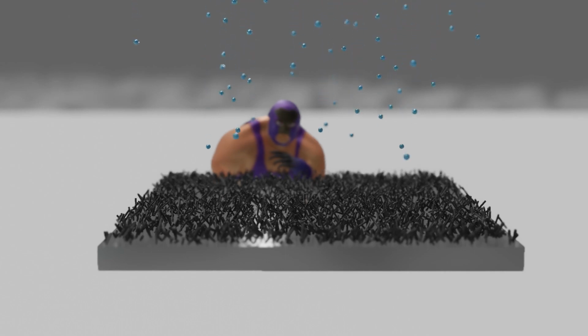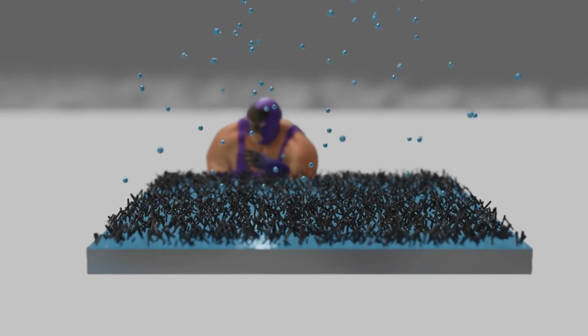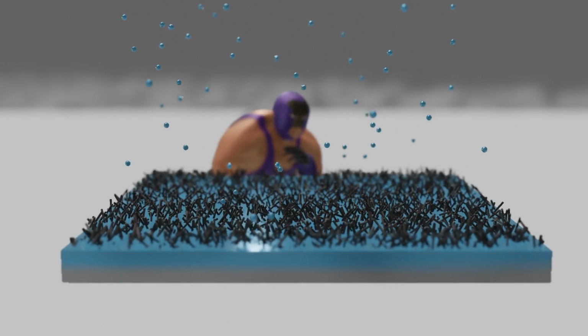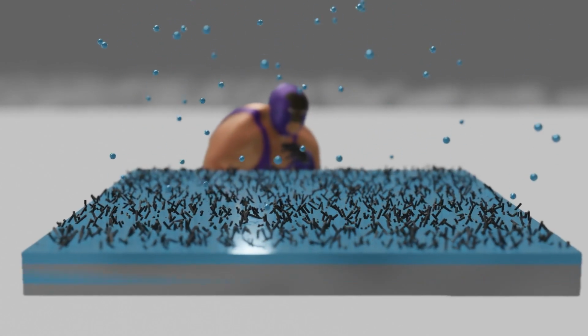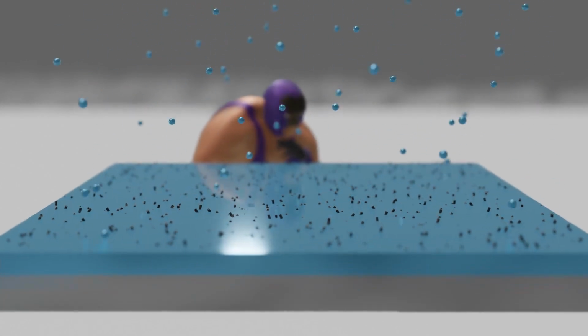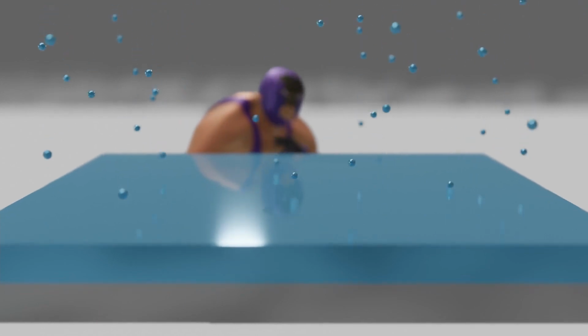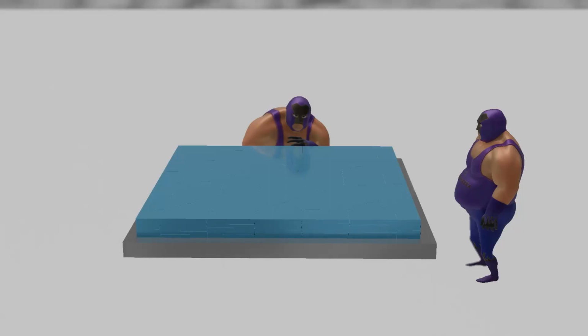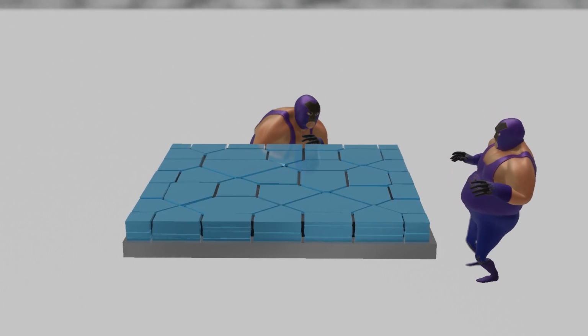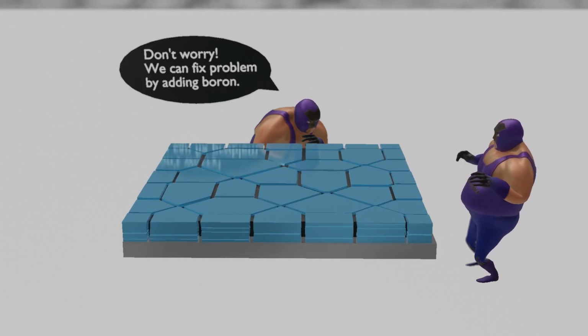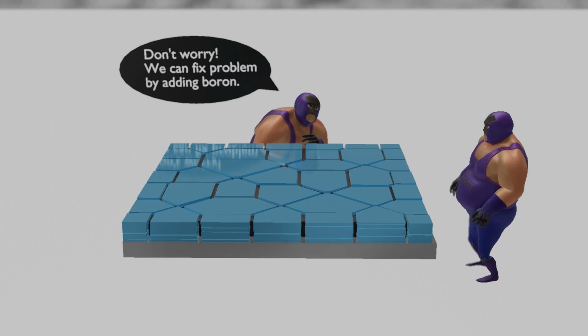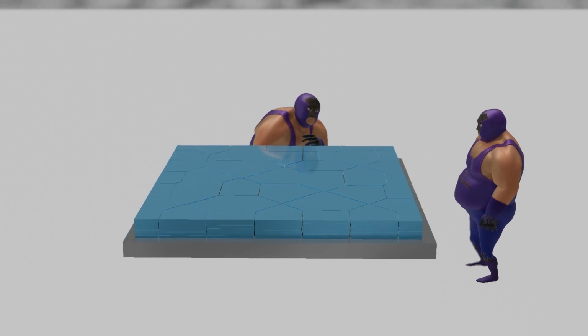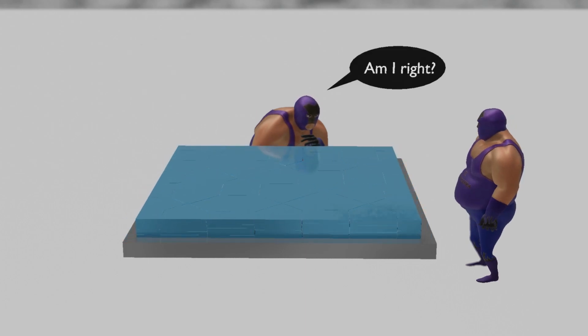Let's take another look. It has recently been shown that the carbon layer of the thin film coated on aluminum foil surprisingly helps sodium ions grow uniformly when charging the battery and inhibits the growth of pointed dendrite forms. Another important recipe is electrolyte additives. As charge and discharge are continuously repeated, cracks occur over time in the sodium metal layer formed in the anode, and it is said that this phenomenon can be prevented by adding a substance containing boron atoms to the electrolyte.